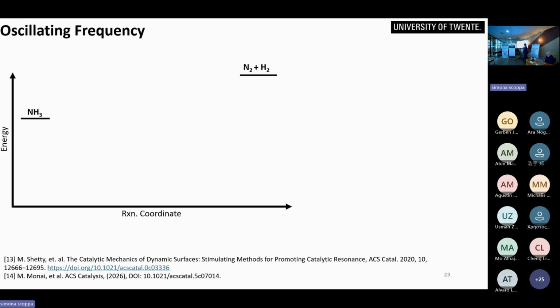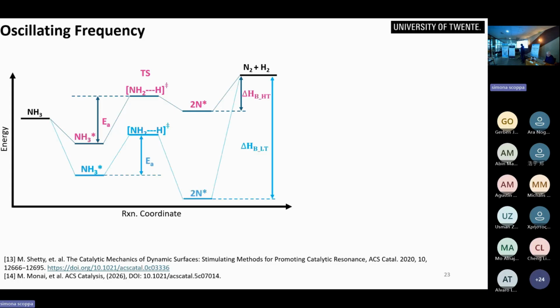So this is not a concept that I invented. It's actually something that is well known in the catalysis community for many, many years. But more recently at the University of Minnesota, it has sort of been brought back to life, these dynamic or oscillation frequencies for catalytic conversion. The general idea is you have a reaction energy diagram where you are operating at temperatures where this, let's say, is your highest activation barrier, the nitrogen-hydrogen bond dissociation. You can actually go from that to a condition where your nitrogen-nitrogen bond formation is the rate limiting step. And so by moving this molecule here to this side and then moving it up by changing this energy landscape, you could potentially use it as a ratchet.